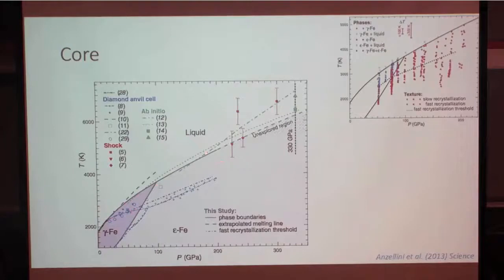And they show this melting curve, which is consistent with the Brown and McQueen shockwave points, and also very nicely consistent with this ab initio melting curve, which is this small dashed line here. This is not an ab initio melting curve, even though they say it is. It's just a pair potential. And it agrees nicely with that. So I think we know the iron melting curve pretty well, actually, now.